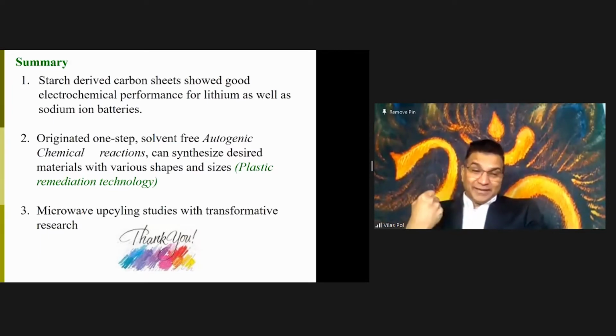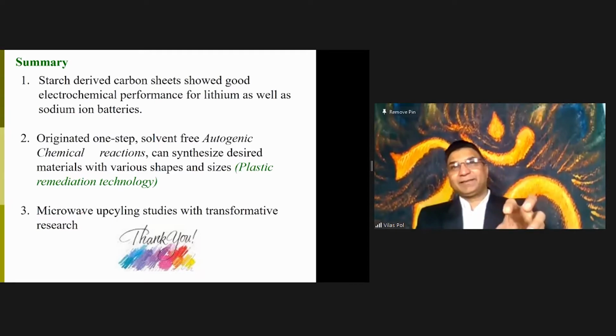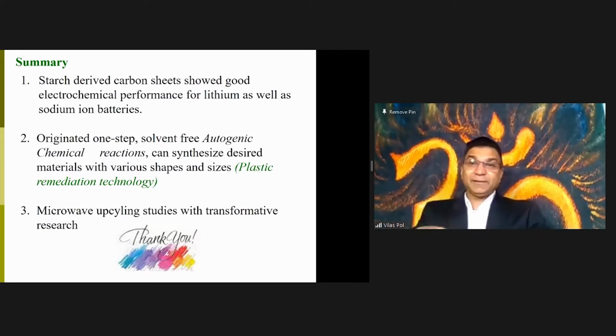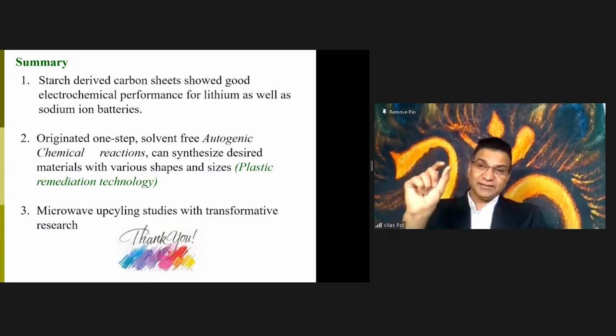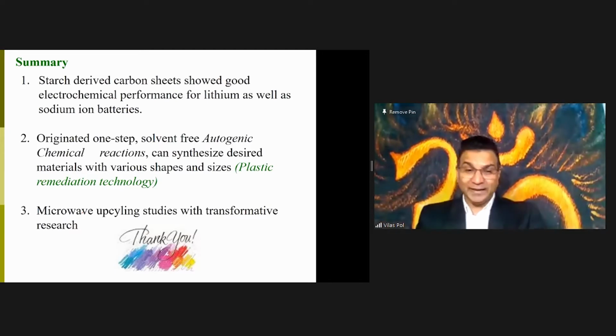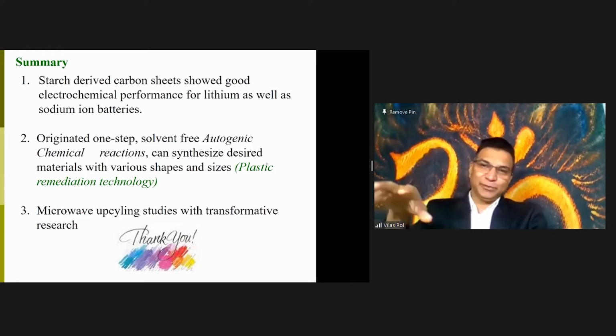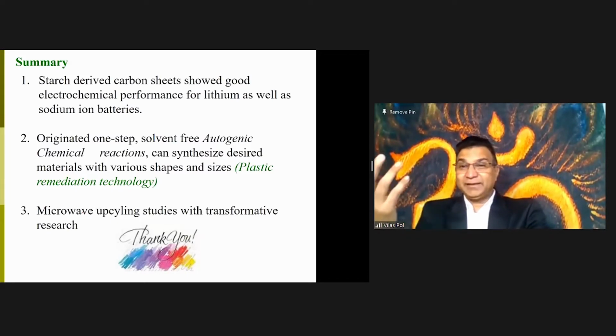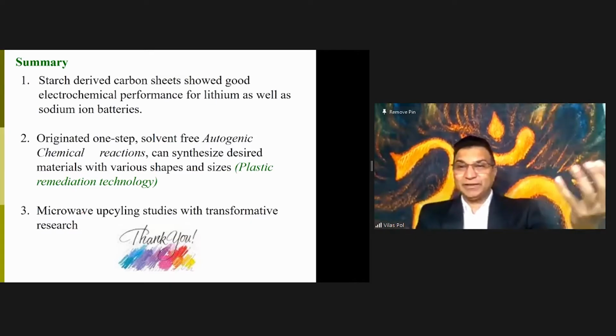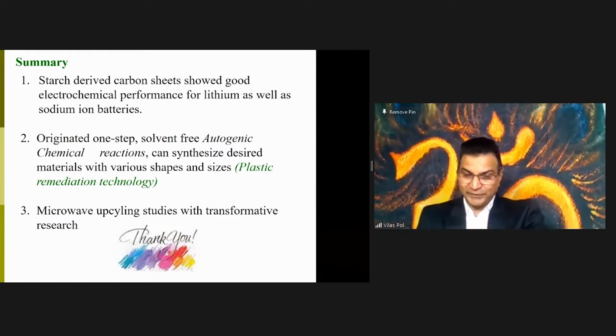To get anything out of that battery is problematic. For example, if you want to mechanically open the battery, then the electrolyte is pyrophoric. If you are putting some mechanical force, the battery can get crushed, can generate some heat, and the battery can explode. So the whole plant can be exploded. So how can you selectively take out that pyrophoric electrolyte from the battery, which is very difficult. People said we will put CO2 gas. CO2 and then the gas goes to the atmosphere and then we make everything contaminated. People said that we will put some acid or base, then we also generate some waste. So really there is no foolproof process.